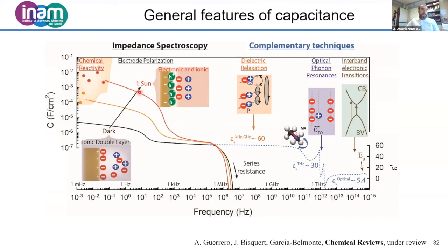As we illuminate, not only will we have ions close to the contacts, but these ions will generate charges and they will modify the band bending as shown by Uli earlier. And there will be electrons and holes also piling up close to the contacts. And in this case, the charge at the contacts will increase dramatically. So we will go to values of millifarads per square centimeter.